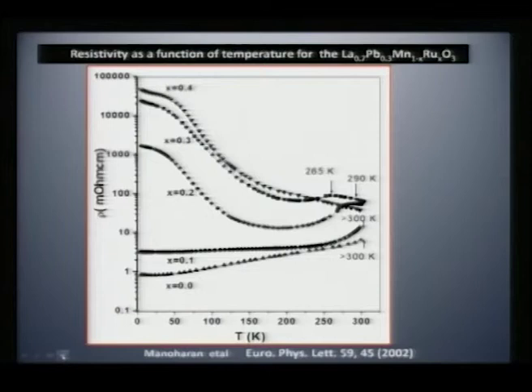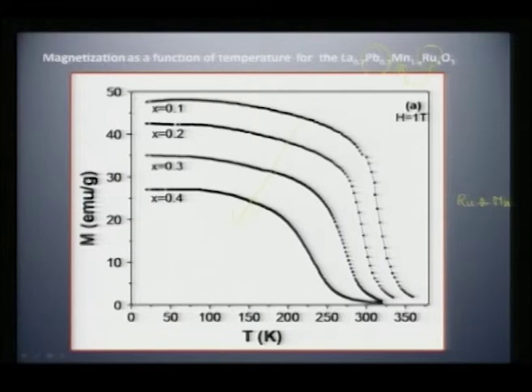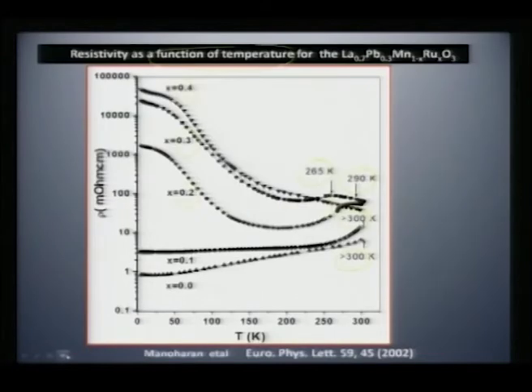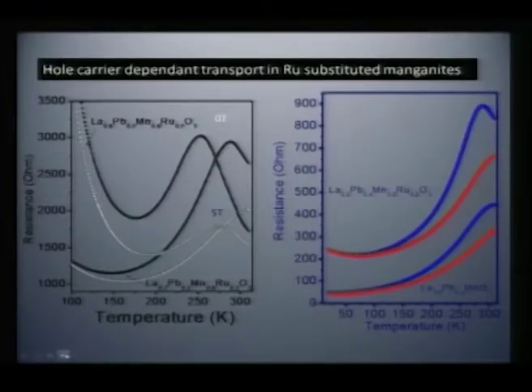This is also pronounced in the resistivity as a function of temperature plot, where you can see the parent compound is showing a clear metallic transition, whereas 10%, 20%, 30% and 40% of ruthenium still shows a clear metal insulator transition corresponding to the magnetic transition which we saw in this case. So if you take this metal ferromagnetic transitions and compare in the next curve with the resistivity plot, you still see a clear correlation happening. So something is very unusual there.